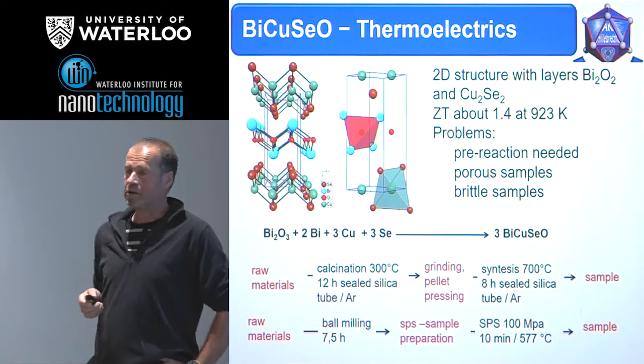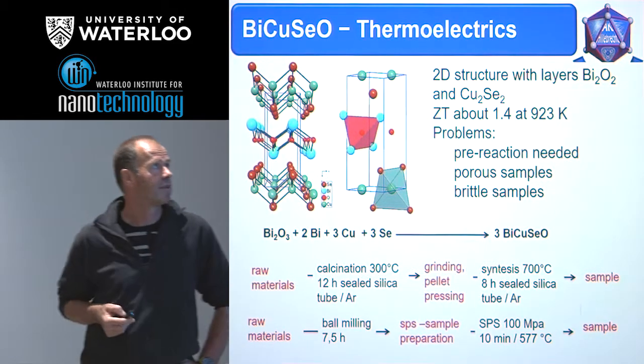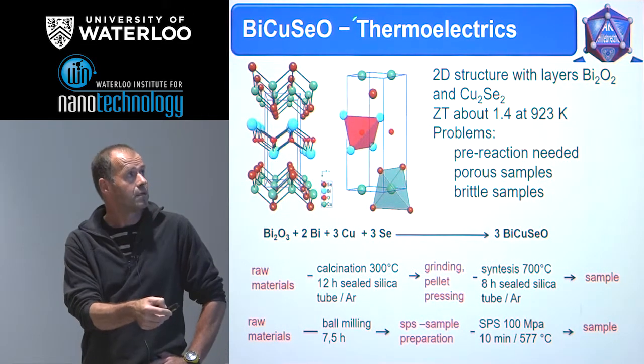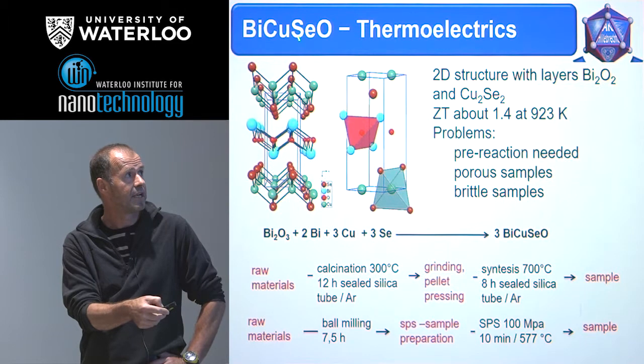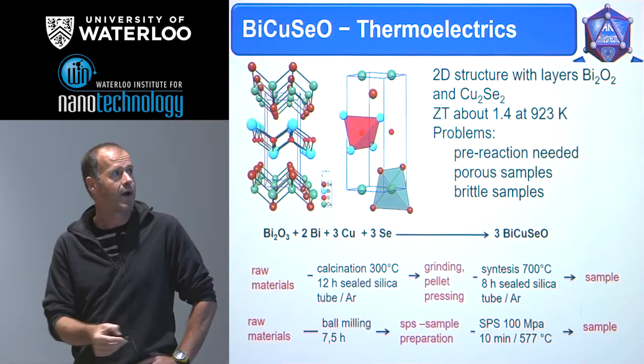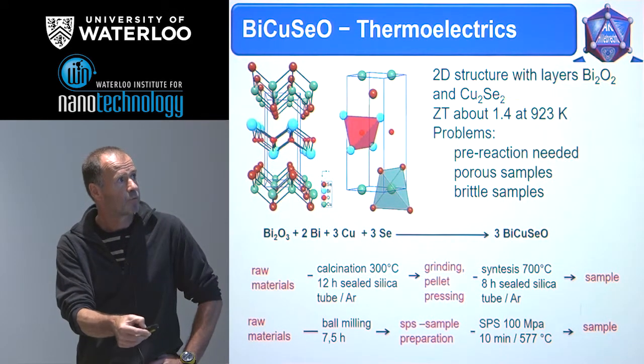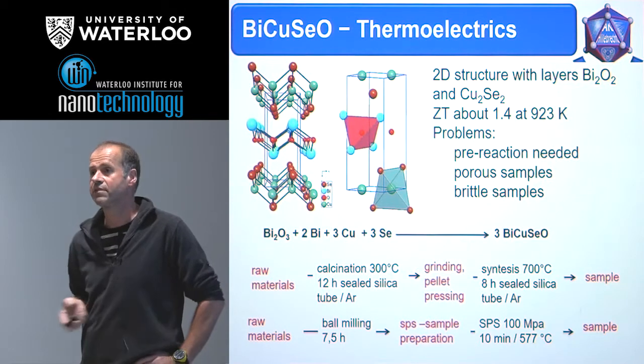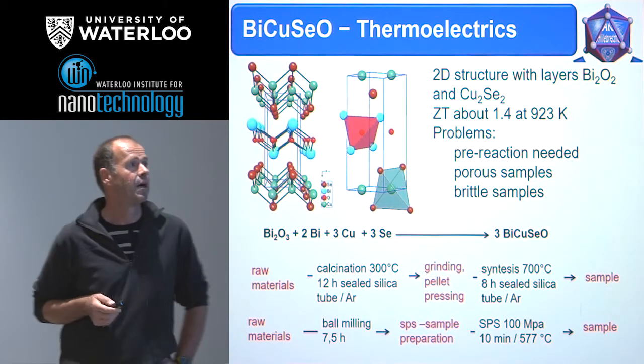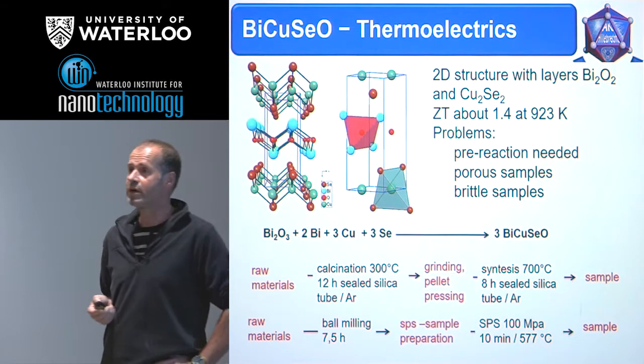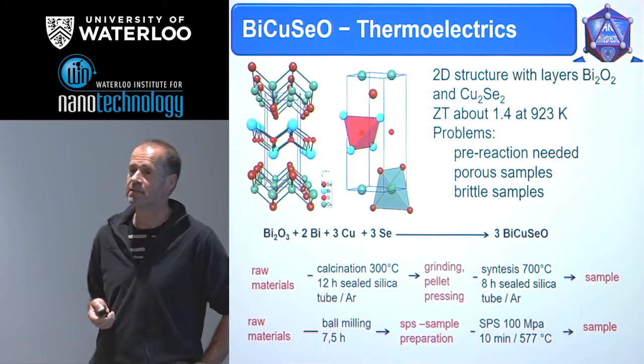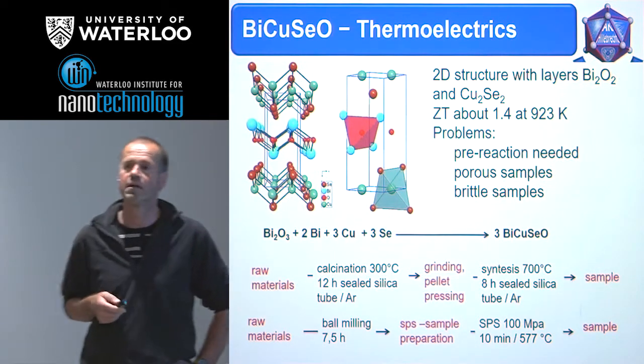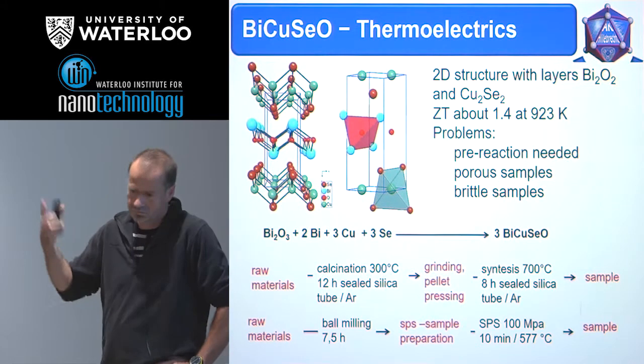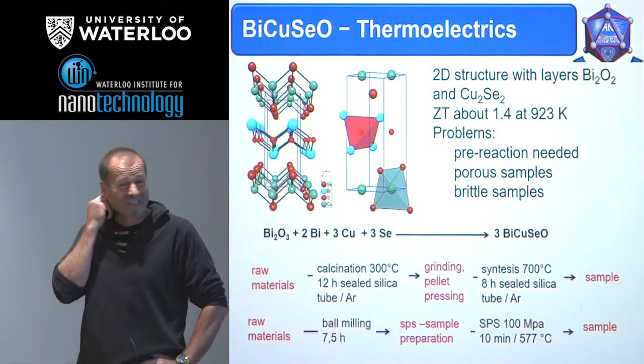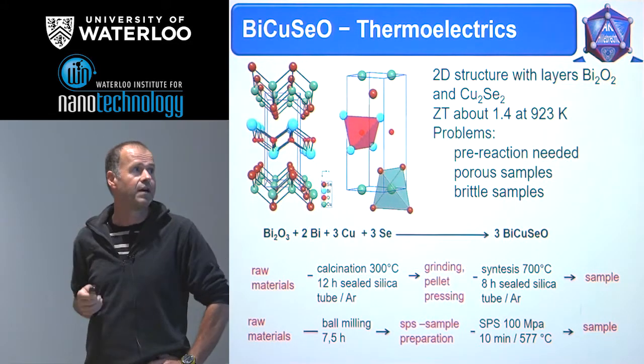Well, a very short project. There's one compound, bismuth copper selenium oxide, which shows quite good thermoelectric properties at around 700 degrees Celsius. A ZT value of 1.4 is not too bad, so it looks very promising, but there are some problems, like in real life.